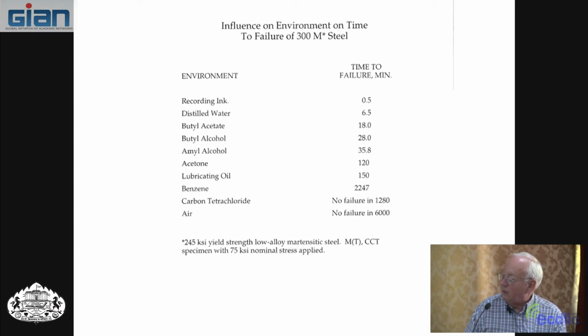They used the center crack specimen, which is the Griffith geometry, and they loaded the specimen to 75. Now 75 is less than 1/3 of that value. So they loaded it only a small fraction of the yield, so yielding wasn't a problem at all. It was well within the linear elastic range. For each case, they put in some environment.